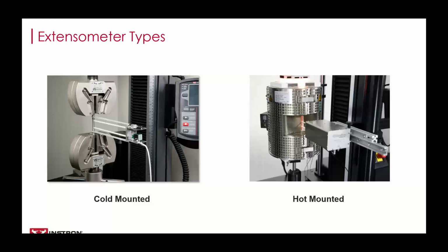Hot-mounted extensometers, on the other hand, are supported by a rigid mounting external to the load string, typically attached to the frame. More preparation is needed with this type of extensometer because the height and alignment all need to be set so that the extensometer arms reliably meet the specimen inside the furnace. However, the benefit of this type is that you don't need your extensometer in contact with the specimen while it's heating up and soaking, which is important for allowing multiple furnaces for high throughput testing.